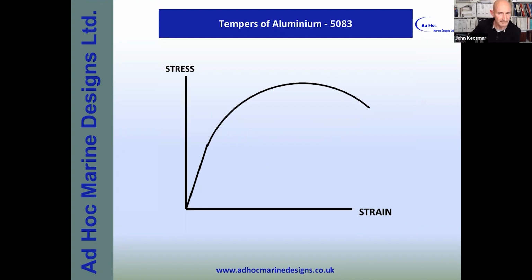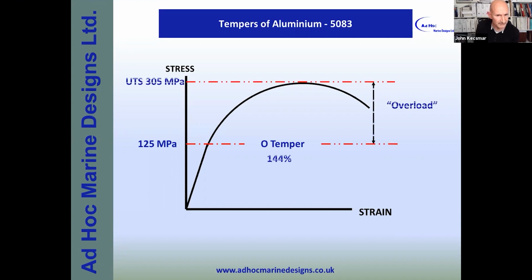If we look at tempers of aluminium, in this case 5083, and a very simple stress strain curve. If we are to plot on here O temper, it has a yield stress of 125 MPa. And then when we compare this to the UTS of 305 MPa, there's an overload. I like to consider this ratio between the UTS and the yield as a percentage in terms of how much capacity the temper can adopt before it reaches its critical limit. And in this case, it's 144%.